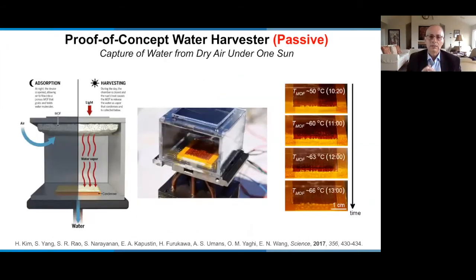So we use this knowledge to design a small prototype to show that in fact the MOF works outside the laboratory. So this is an almost handheld device. The MOF is put on a surface, and this is almost like a jar, and you have the MOF in the jar, and at night you open it. Water from the atmosphere goes into the MOF. During the day you close it, expose it to the sunlight.